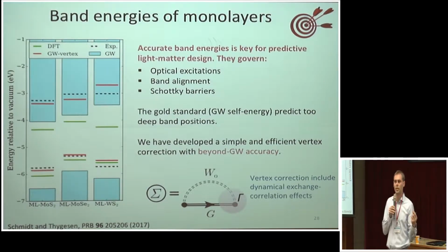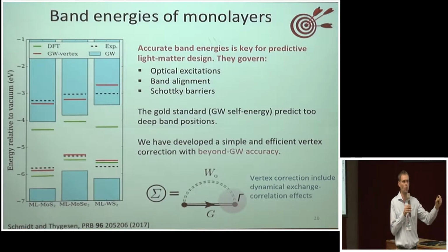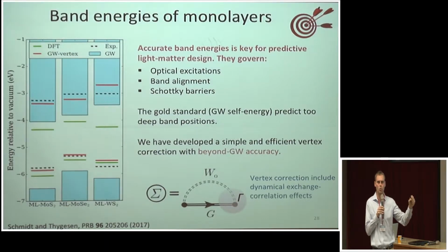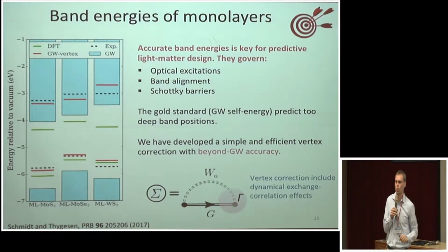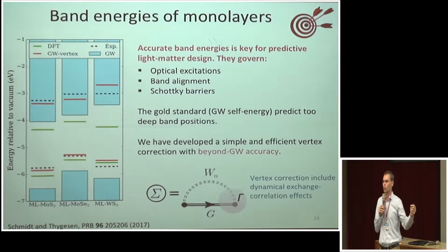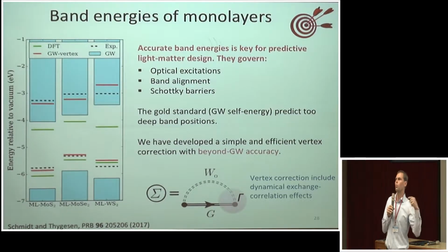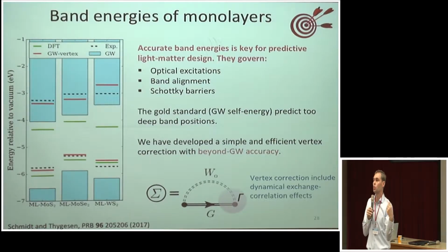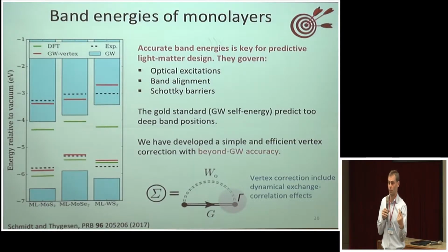What it does physically is that once we create the hole, okay, think about the quasi-particle band structure, we shoot an electron out, we create a hole. This hole has a Coulomb potential associated with it, so it will polarize the material. Once it polarizes the material, it creates a change in the density of the host material. And then the hole interacts with the potential set up by that induced density. And that's the self-energy. Okay?